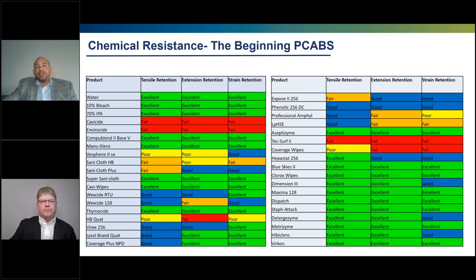So excellent's gonna be in green, it goes all the way down to failure. Typically green's gonna be anytime we have 90% or more tensile retention. Failures are gonna be anything 60 or below. And primarily we wanna see things stay above 80% for the most part. So this is where we're at today. Typical pricing for pre-colored PC-ABS is going to be $2.50 to $3.50 a pound on large volumes, and goes up obviously if the volumes decrease, releases decrease to customer.